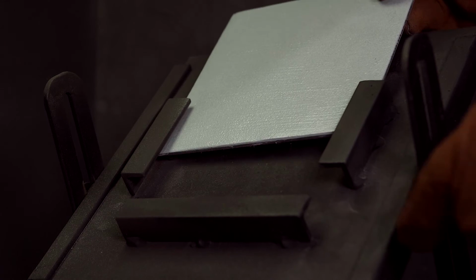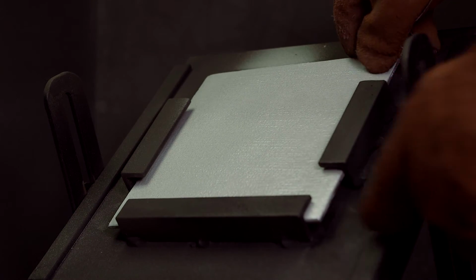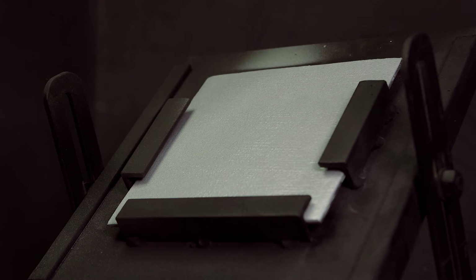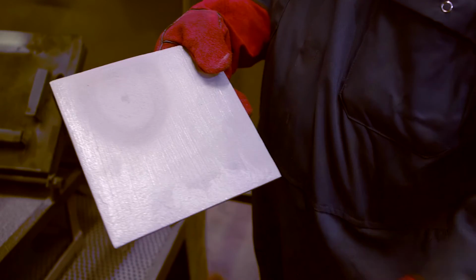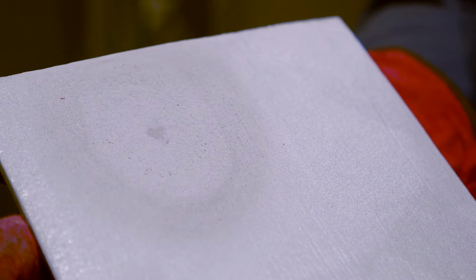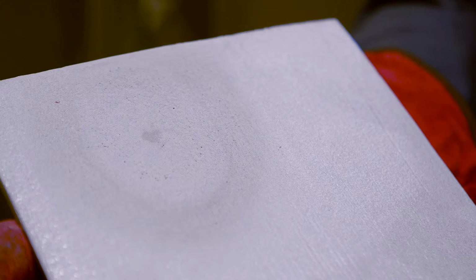The test is carried out by coating a sample plate at a given thickness, and when fully cured, it is weighed and placed on the sample test bed. The apparatus is started and the test is conducted for a given period of time, usually 2 minutes, or until the substrate becomes exposed. The results are given as weight loss or time to substrate exposure.